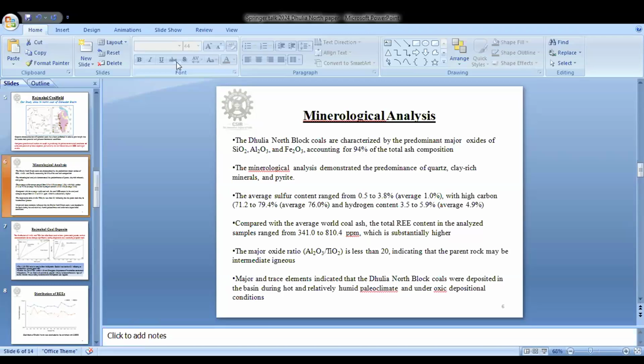High carbon content from 71 to 79%, average was around 76%, and hydrogen content usually is around 3.5 to 4, so here it was 3.5 to 6%. Compared with the average world coal ash, the total rare earth content in the analyzed samples ranged from 341, some of the lowest concentrations, to almost 810 ppm, which is substantially higher than the world coal ash. I'll come to the graph later on.